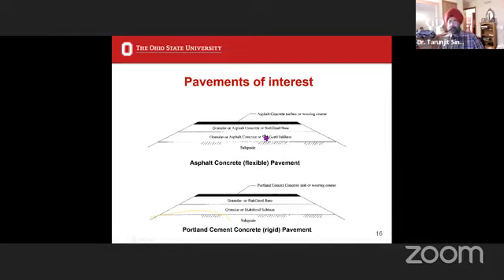However, before that can be done, the stiffness reduces so much that this particular layer has rutting in it. As a result, traffic that goes over it is bouncing, boom, boom, boom. So the pavement has already failed, not from a structural perspective, but a performance perspective, because the stiffness has reduced significantly and it is no more serviceable. So you don't have to wait for the strength also to degrade, because it cannot be used as a road.